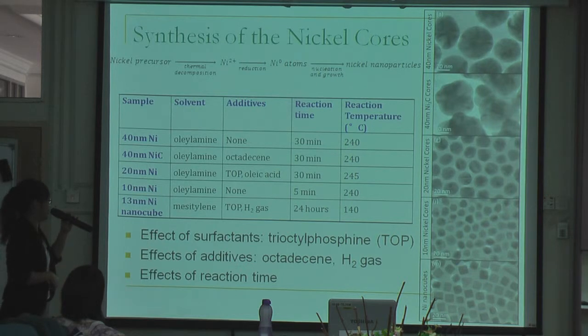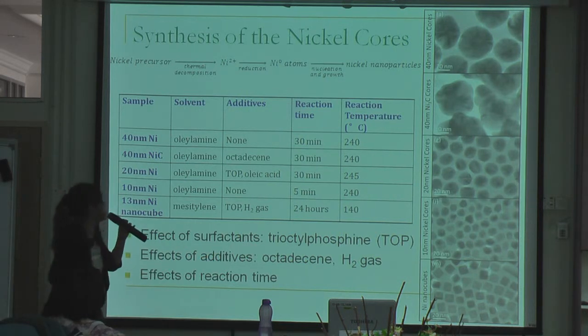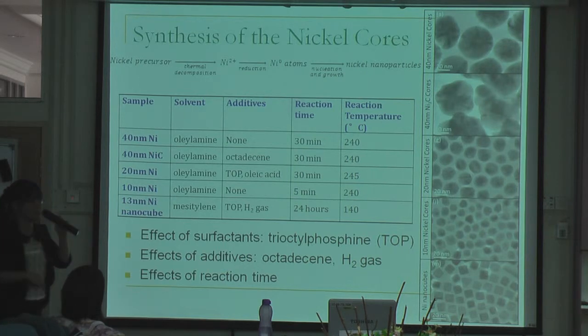Basically, the special ingredient here was the hydrogen gas, and then the preparation in a pressure vessel, in order to produce such kind of cube-shaped nickel nanoparticles, which are quite special. So once I have successfully prepared all the different kinds of nickel seeds, I moved on to study the coating of these nickel seeds with cadmium selenide and the chemistry behind it.